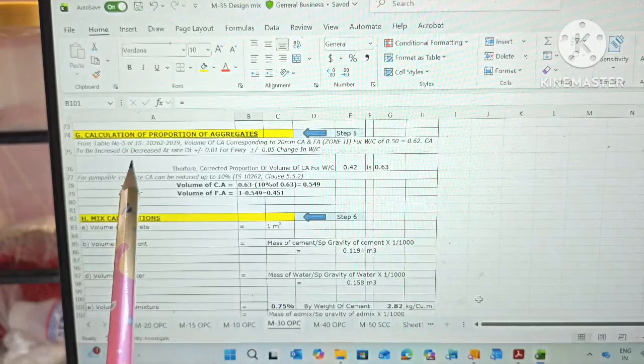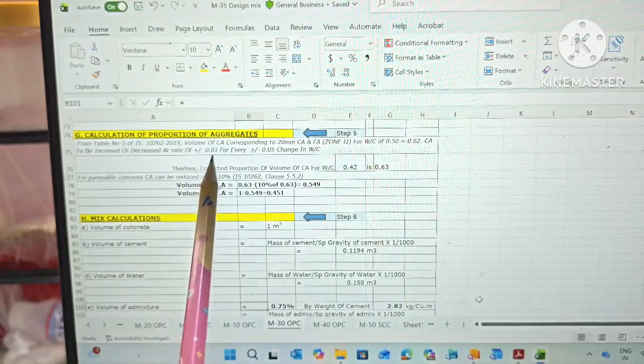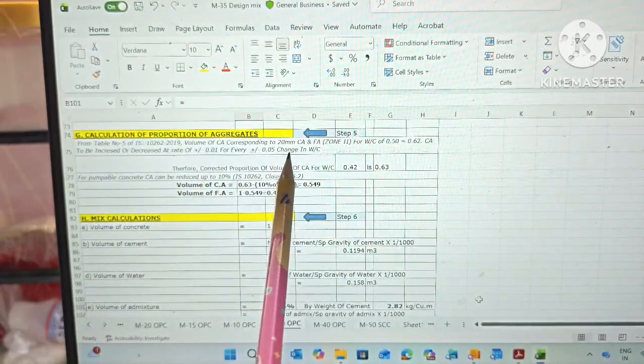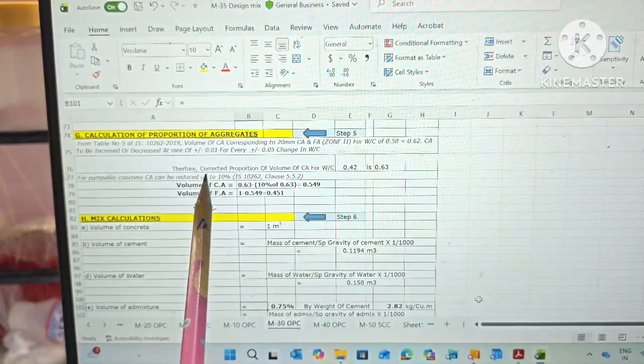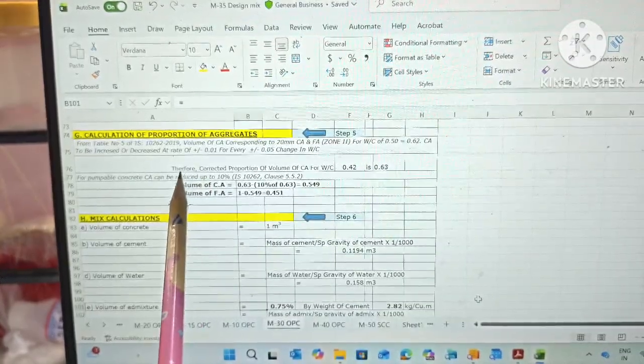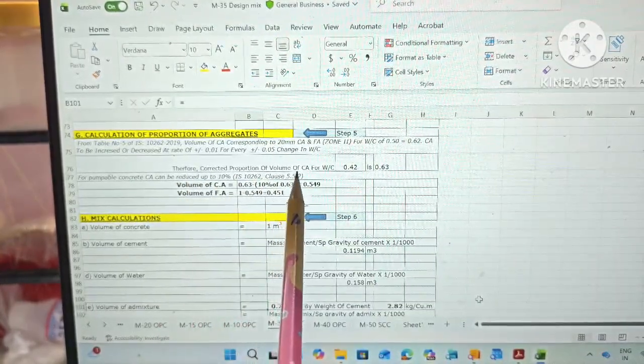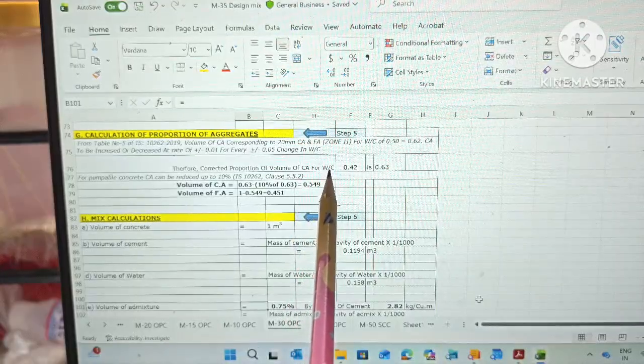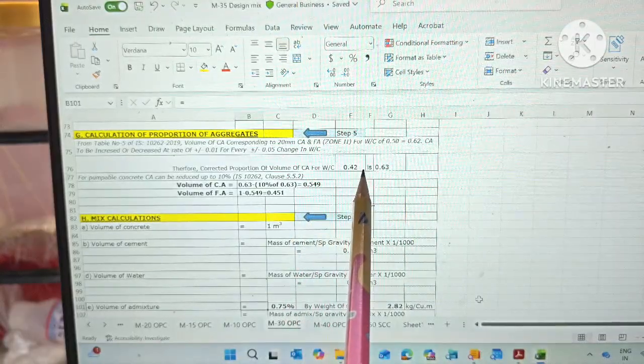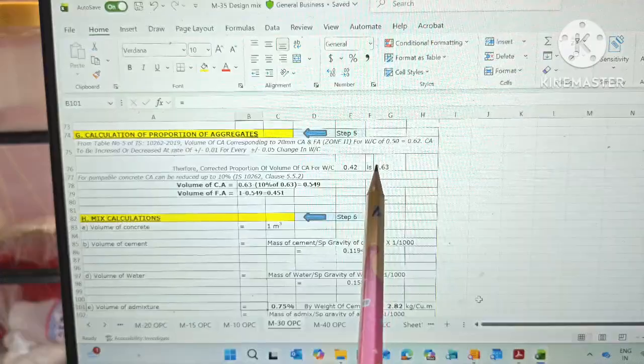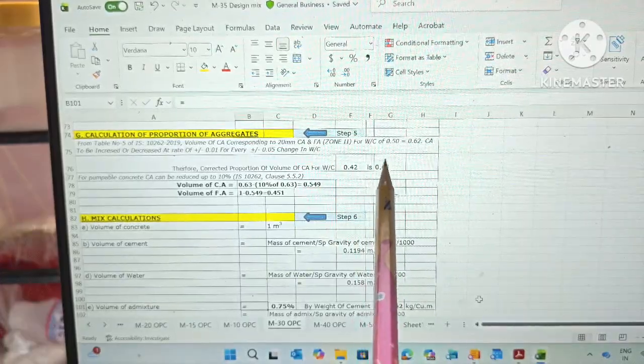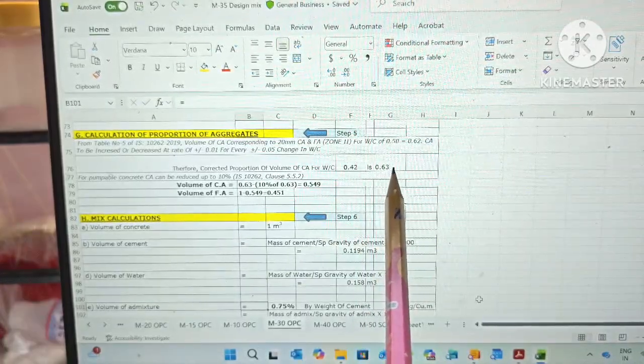Coarse aggregate is to be increased or decreased at the rate of plus or minus 0.01 for every plus or minus 0.05 change in water cement ratio. Therefore, the corrected proportion of volume of coarse aggregate for water cement ratio 0.42 is 0.63. Now, how is this 0.63? Now I will explain to you the calculation of 0.63.